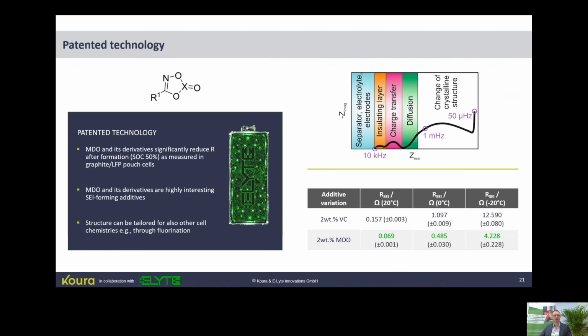So here I'm talking about graphite LFP cells, where we also introduced our molecule at 2 weight %. We compared to VC. We did some electrochemical impedance spectroscopy measurements. And what becomes clear is that we can decrease internal resistance. This gap is even more dramatic when we go to low temperature. So what I want to point out here for special application is low temperature performance, but we are also focusing on high charge rate. Yeah, so fast charging, of course, when you think about electric mobility, this is also the goal, to get the battery charged in a very short time.